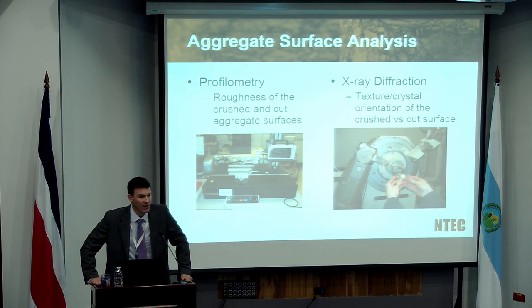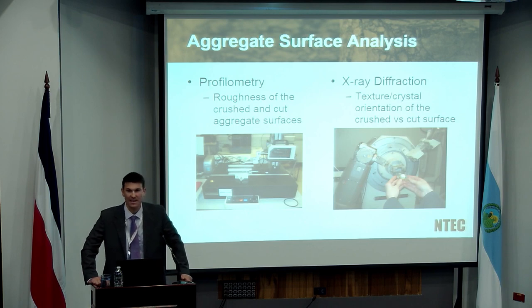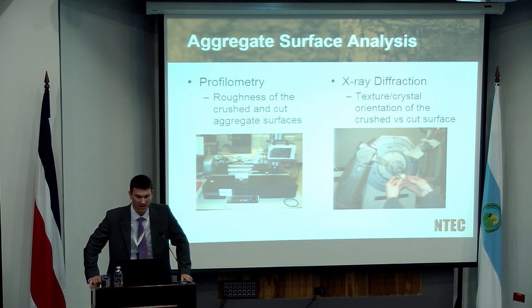The important thing, though, is to make sure that we haven't changed everything in terms of what we would have in an asphalt mixture. So we were very keen to find out what was the surface texture, what was the surface profile of those particular substrates compared to a normal aggregate. And we can do that with a number of different techniques. The first technique is to use something called a profilometer, where effectively you very accurately measure the surface roughness of your individual particles. And I'll show you a few examples, a few diagrams of what we found.